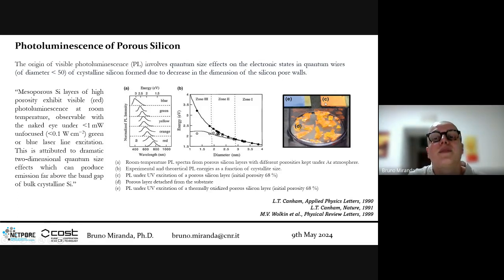Now, here, for example, you can see the photoluminescence of porous silicon under UV excitation with an initial porosity of 68%, but this is when you detach it from the substrate, so the detached membrane.